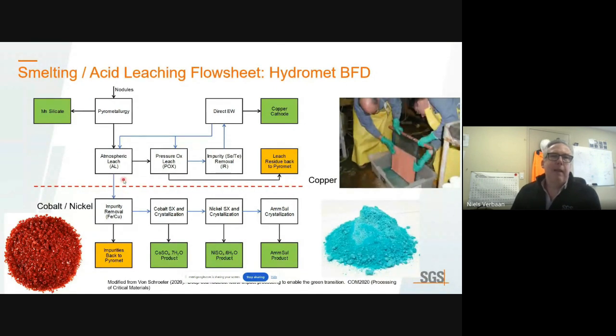Here's the flow sheet, and Ron, now that I know that you're online, you may recognize yourself here. That's you out there, and this is me a really very long time ago. But here's a flow sheet that's being used. So the nodules go through the hydrometallurgical steps. It leaches in an atmospheric and a pressure oxidative style leach. Copper is recovered here as cathode, and I threw this picture in here just to show that even though right now I do a lot of talking, there was a time where I was still actively doing test work, and this is myself and Ron both online here cleaning washing a copper cathode here. The atmospheric leach slurry is further processed, impurities are removed, solvent extraction is used to ultimately produce cobalt sulfate and nickel sulfate.